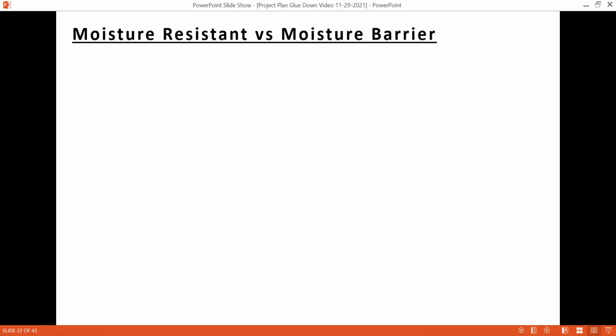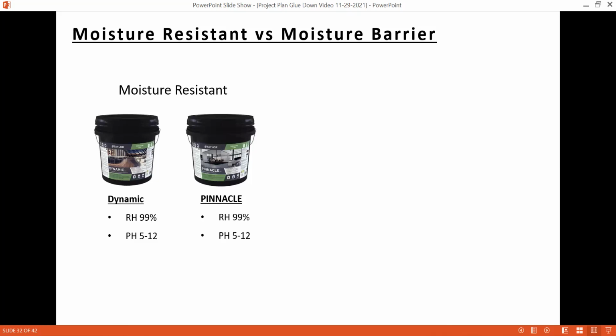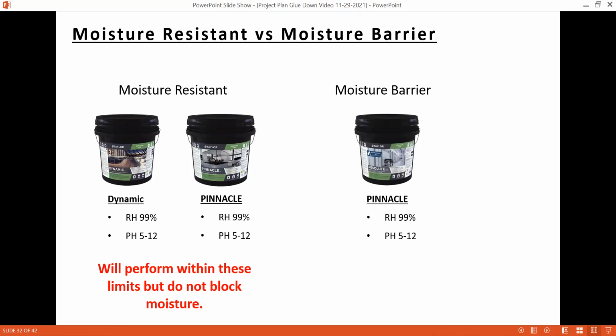It's important to discuss the difference between moisture resistant and moisture barrier. Taylor Dynamic and Pinnacle are moisture resistant adhesives. This means that they will hold their bond up to the moisture limit specified, in their case up to 99% relative humidity. But they do not block moisture from reaching the flooring. Taylor Resolute is a moisture barrier adhesive. It will block moisture from reaching the flooring.